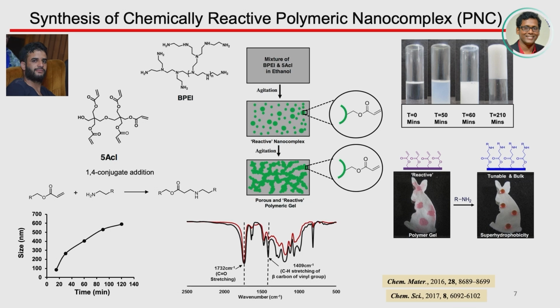Now, this nanocomplex is not like other regular nanoparticles and nanocomplexes. This nanocomplex has residual acrylate groups. As is evident from this FTIR spectra, the CH stretching for the beta carbon of the vinyl group appears at 1410, which is an unambiguous signature. And you can see another signature for the carbonyl, but once it goes through this 1,4-conjugate addition reaction, the carbonyl remains as it is. It's just the vinyl group that vanishes, right?